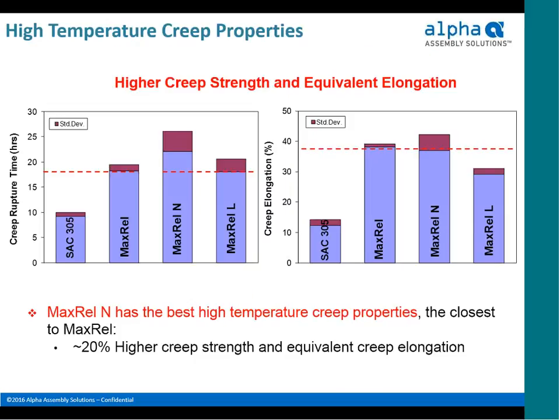What we see in this graph here is a way to show the data and the differences between, again, SAC 305 and the Maxrel family of high reliability alloys. What you see is a pretty significant difference in the creep rupture time in hours, so higher bar is better on the left-hand graph. And you also see a higher amount of creep elongation percentage, meaning that it elongated more before it ultimately failed. So even after it deformed, it still remained intact for a longer amount of time before it failed. Again, showing a quantified way to demonstrate that the Maxrel family of alloys provide superior creep properties compared to SAC 305.